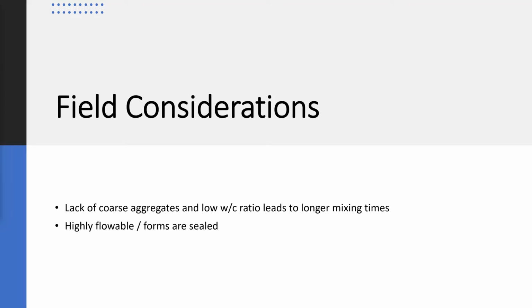Some field considerations to take into account when using UHPC: due to the lack of coarse aggregates and the low water to cement ratio, both of these lead to longer mixing times, which is typically about 20 minutes for drum mixers. If you add fiber reinforcements, which is typical, it also adds time as you have to put in the fibers in a deliberate manner to ensure uniform distribution through the mixture without it clumping. Also, as you mix, you have to take into consideration the temperature, because if you mix for too long, it increases the temperature, which can result in a stiffer than desired mixture. And due to its highly flowable nature, forms are to be sealed in a secure and deliberate manner in order for there to be no seepage.